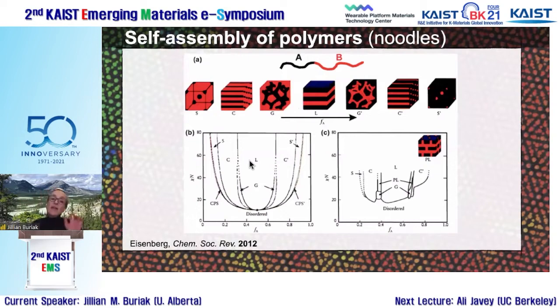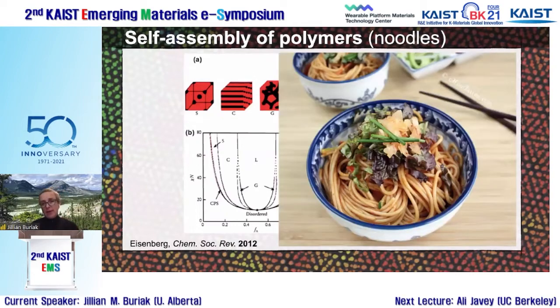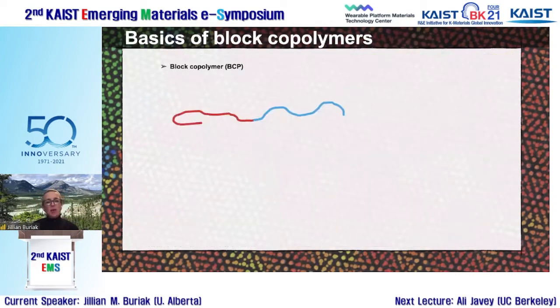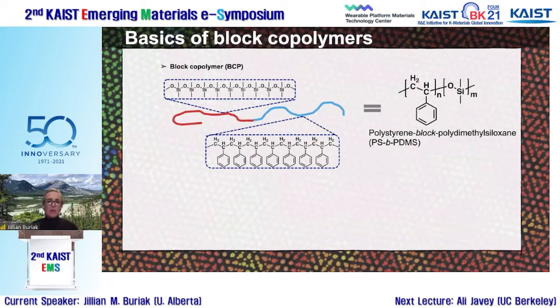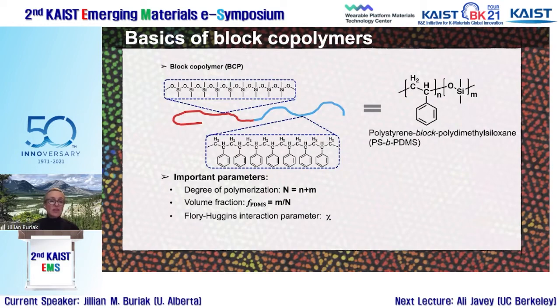So pretty interesting. And then when you take these block copolymers, so I get these noodles, depending on the chemical composition, depending what you do with them, and you confine them into a single layer, then you can use this as a template for lithography. And so the block copolymers that we work with, a lot of them have this chemical composition that you're going to see throughout this talk. This one has one block, which is PDMS, polydimethylsiloxane. And the other block here is just polystyrene. And so that's just abbreviated as PS-b-PDMS, b meaning block. So just a very simple one.